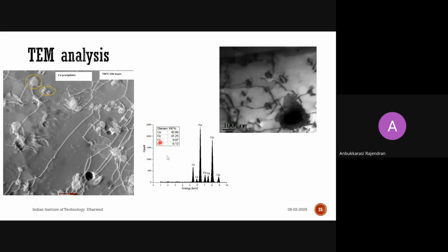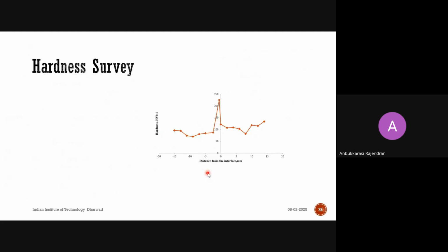Even TEM can provide chemical analysis through EDS. For particle composition, this is the precipitate. These are very fine precipitates, and you can see the scale is in nanometers. The composition of these fine precipitates we are even able to measure using the EDS detector, but it is attached to the TEM, not the SEM. So composition mapping can be done for variations in the composition, and even hardness plots can be made from one region to another. That gives a feeling of the hardness variation from one region to another.